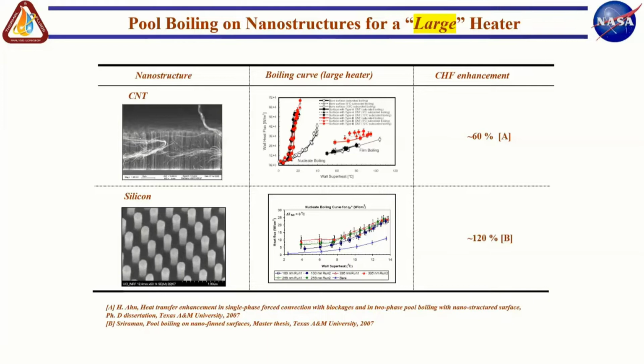And so we went back, we took that same type of silicon wafer, we etched nanofins. These are about 100 nanometers in diameter on an 800 nanometer pitch, and we could grow them anywhere between 10 nanometers all the way to 700 nanometers in height. And again, there are a lot of nuances here, but I'll just focus on the critical heat flux. And silicon with a lower thermal conductivity gave a 120% enhancement in the CHF, which again did not make sense initially.